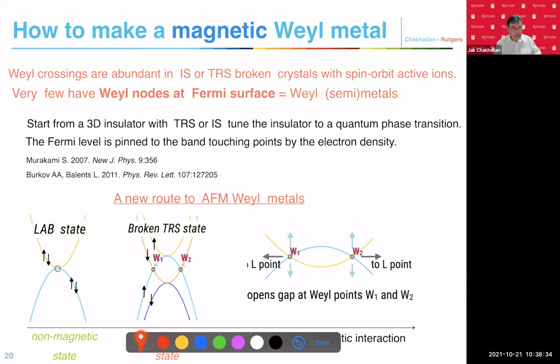Of course, if you make the material more and more magnetic, going to low temperature, the Weyl points start moving because they repulse each other to the edge of the Brillouin zone. Once they reach the edge of the Brillouin zone, they annihilate because they have different chirality, and boom. The gap opens up. So it becomes a trivial insulator, of course a Mott insulator, but topologically trivial.